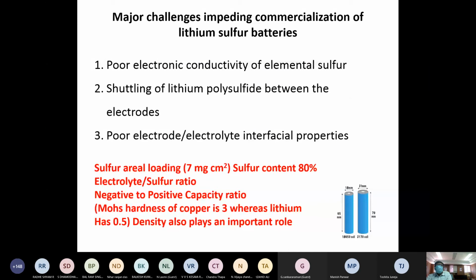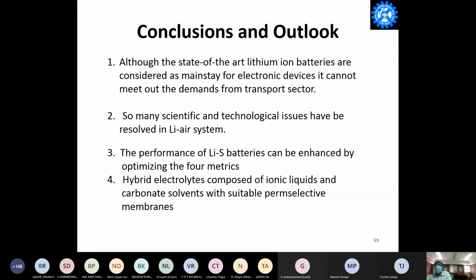And another one is sulfur areal loading, that you have to reach 7 milligram per centimeter square with a sulfur content of 80%. And the electrolyte to sulfur ratio is also another problem, and negative to positive capacity ratio. All the six challenges have to be addressed before this commercialization. So we strongly hope this will be commercialized in another 5 years with higher capacity and at low cost.